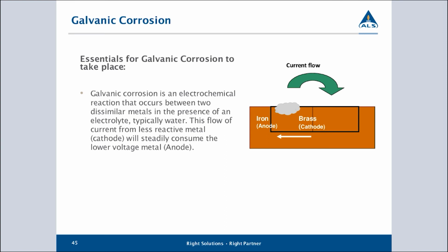Your galvanic corrosion, generally this is a design problem. If the system is designed properly, this shouldn't be an issue, but it's essentially where you have dissimilar metals that have been bolted together. You can get electrical potential driven between them, and this can drive a corrosive action through the flow of electricity from simply bolting these two bits of metal together. To be honest, in most installations, this is not a big problem. But where you've got custom-built equipment, this could be a problem. And in the marine world, this is particularly problematic because there might be salt water in part of the systems, and salt water is particularly good at driving this kind of corrosion.